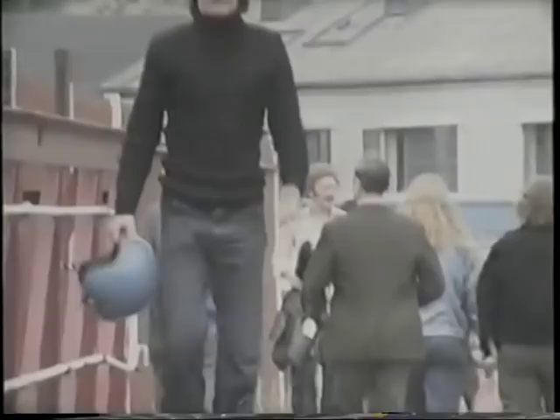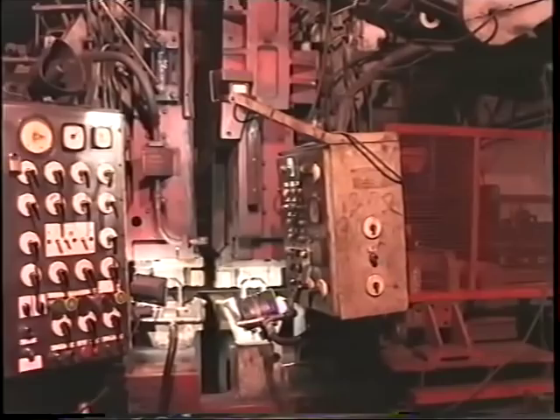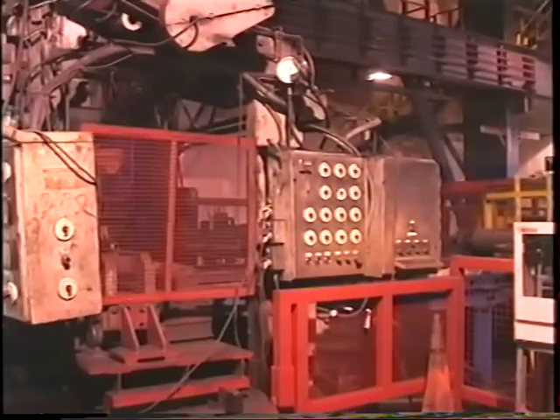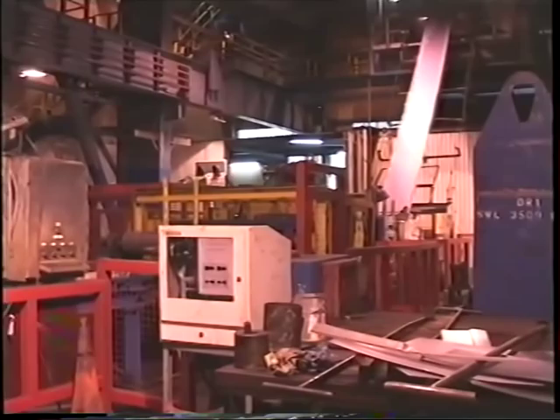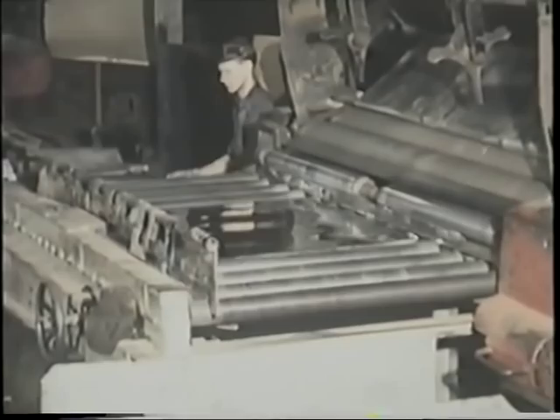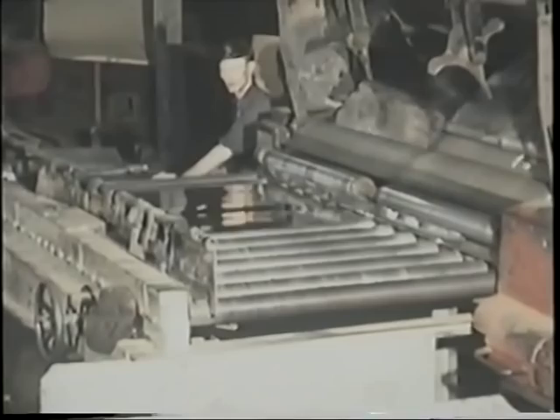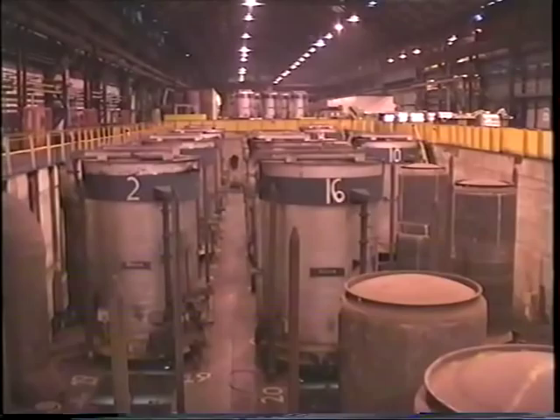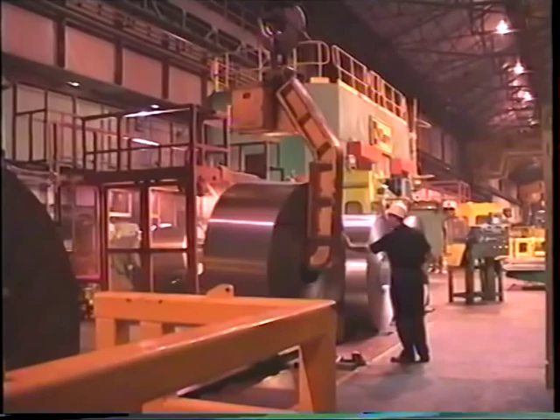By 1971, construction began on a new hydrochloric pickling line, an $8.5 million investment that would be commissioned in 1974. The future looked even better when in 1973, British Steel Corporation announced a multi-million pound Phase 1 tinplate development for the works. Amazingly, between 1976 and 79, this massive scheme was carried out with production remaining very largely unaffected. Number 5 electrolytic cleaning line was installed together with 51 single stack annealing bases, a double reduction temper mill, and a coil preparation line.